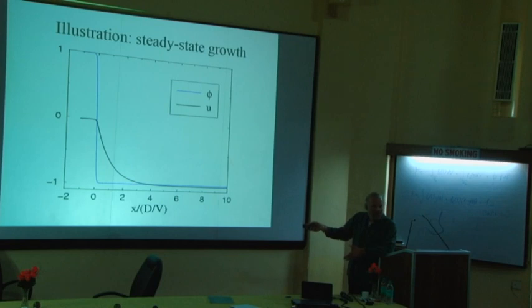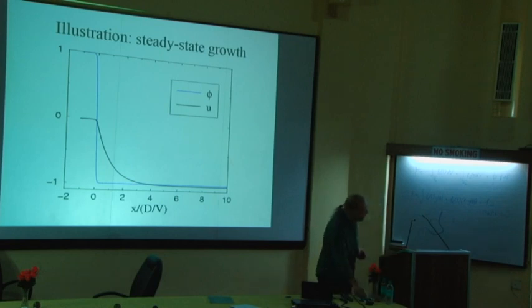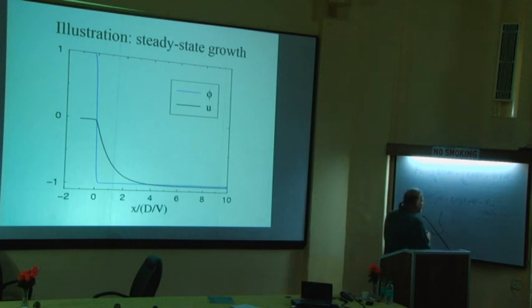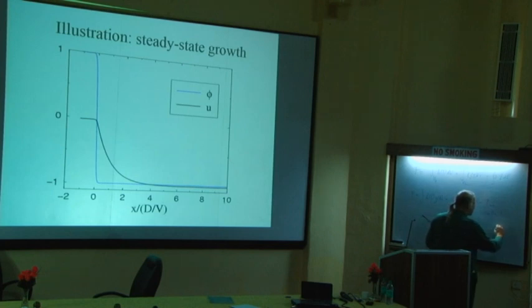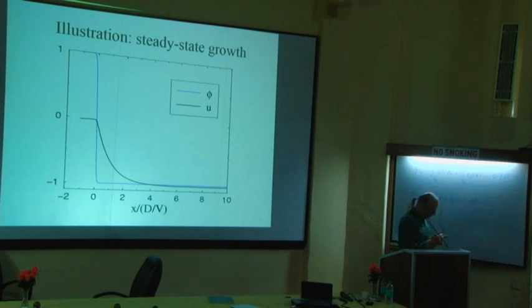which is precisely what the Stefan condition would predict. Remember, the Stefan condition was V times L is equal to the difference of -D grad U in the liquid plus D grad U in the solid. So if you take this at face value, of course, since V is finite here, that means that there's a jump between the gradient of U in the solid and the liquid.